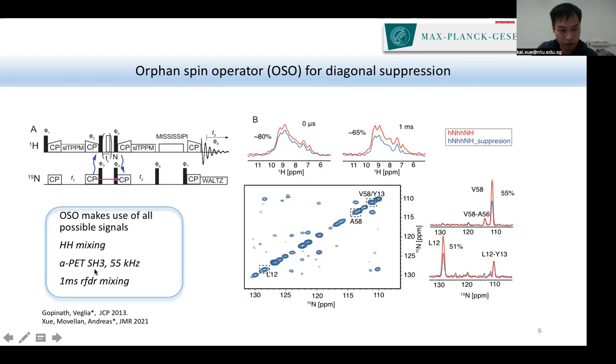It's a deuterated protein, and we spin it at 55 kilohertz. As you can see here, for the diagonal peaks, we managed to have approximately 50% suppression while not sacrificing peak intensities at the mixing region.